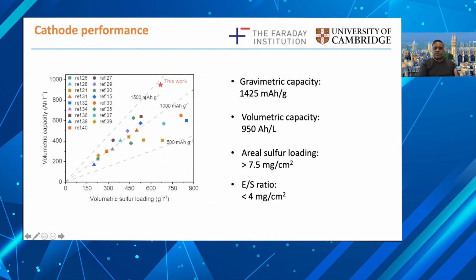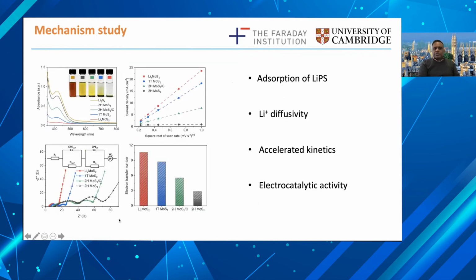references, one can see that these 1T phase MoS2 cathodes work extremely well in terms of the volumetric capacity and the amount of sulfur loading. They're amongst the highest that have been reported, with electrolyte to sulfur ratio that are less than 4 milligrams per centimeter squared. So it's really encouraging. And the main reason for this improved performance, we believe, is that because the 1T MoS2